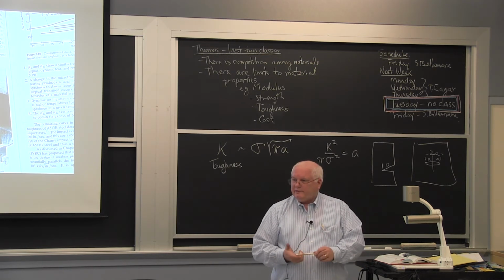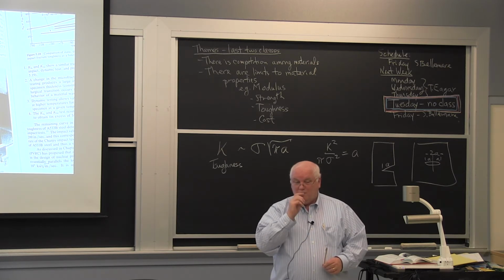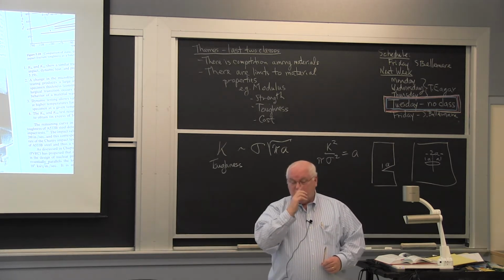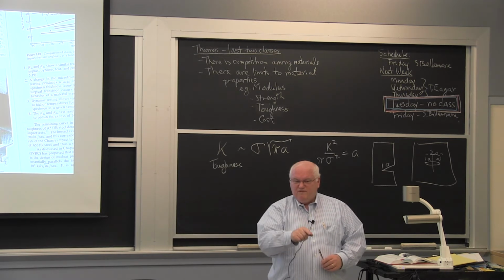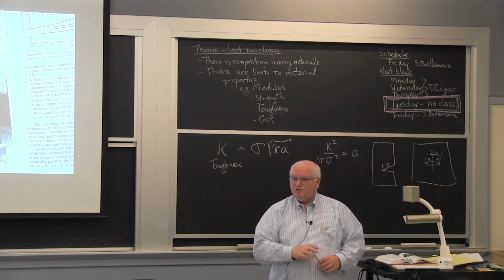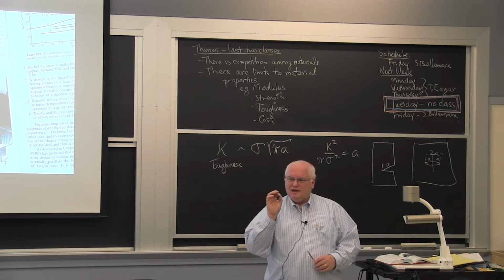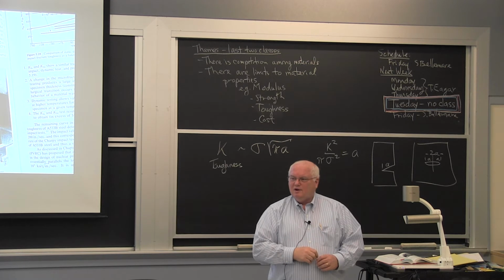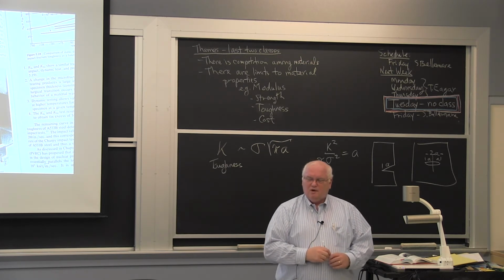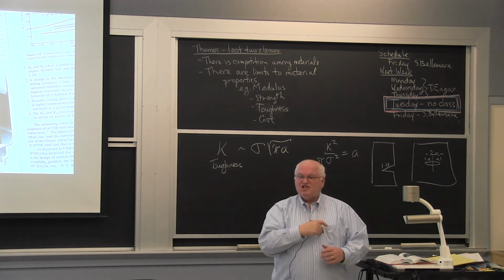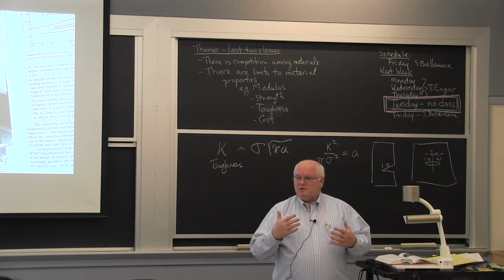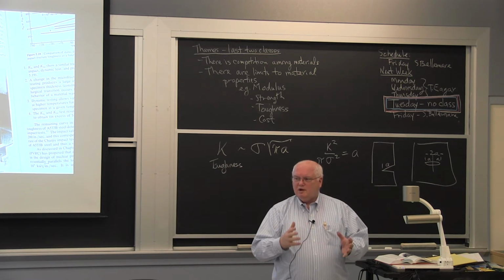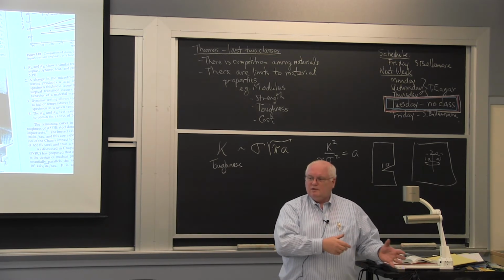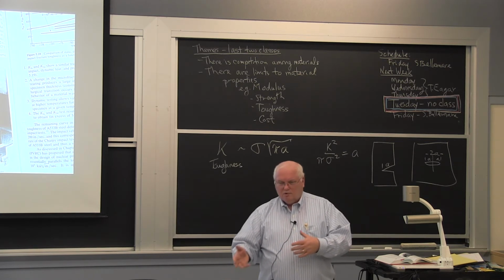Well, it turns out they did it just like everybody thought they did, except what he found out in about the mid-1970s is that granite is a 3-phase material. Got 3 different types of rock in there, and you actually form little cracks at the tip of that notch that toughen the material. So if you measure the fracture toughness of granite, because it's a composite material, it has about 2 or 3 times the toughness that you would predict from the toughness of silica or the toughness of feldspar, or what's the other one? I can't remember.